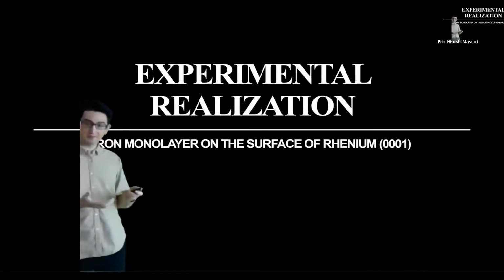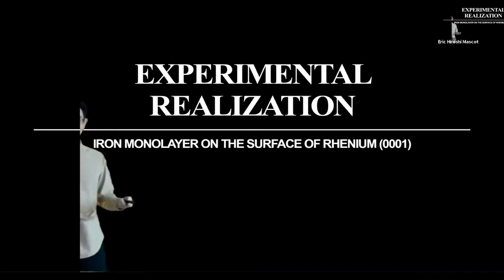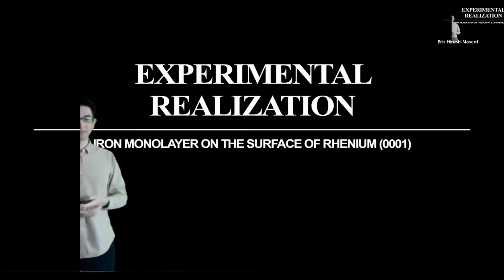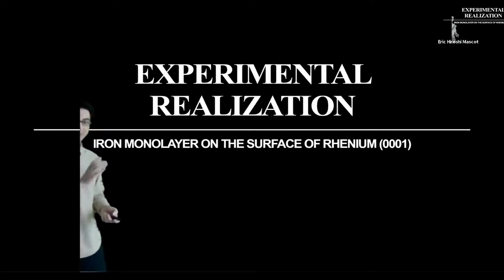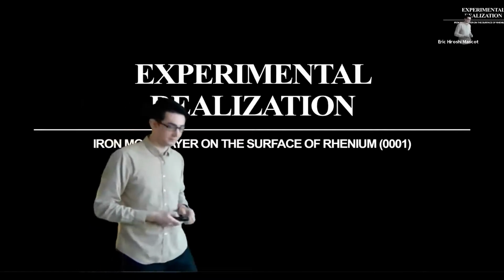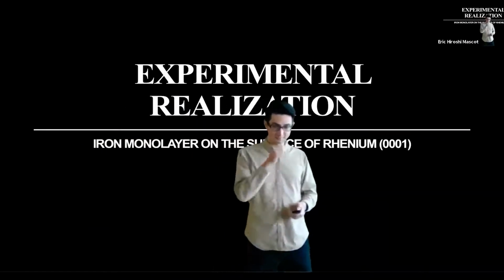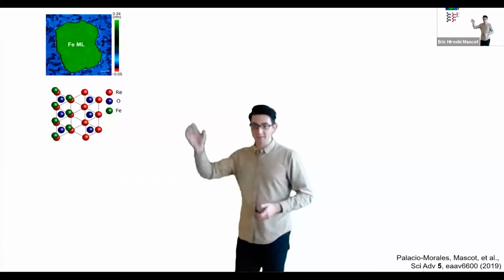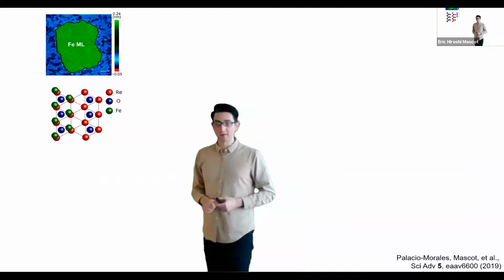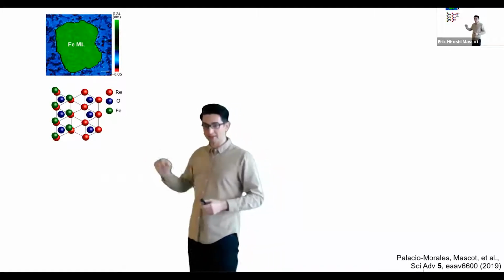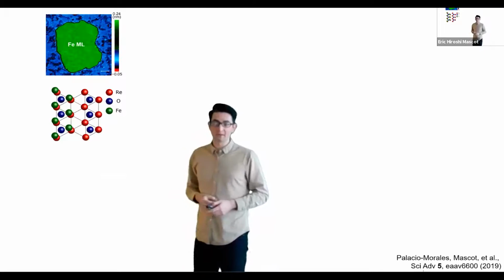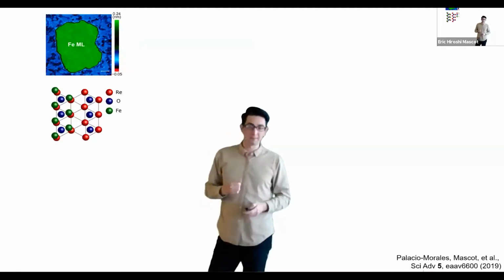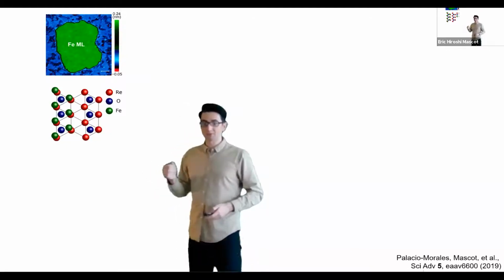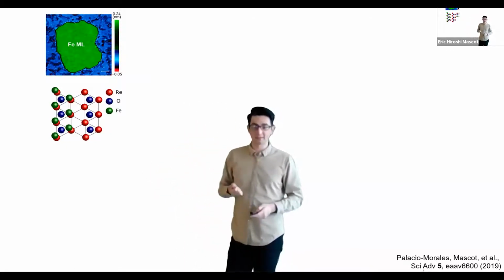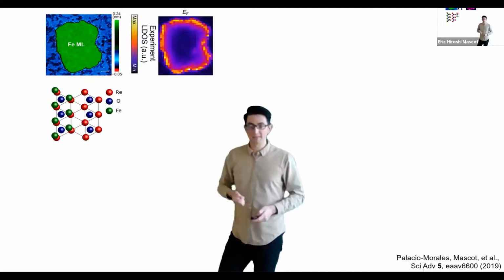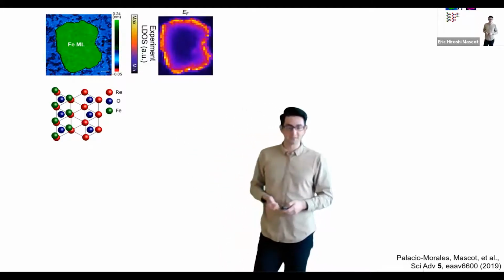So that's a theory. Do we actually see this in an experiment? We collaborated with a group at the University of Hamburg who grew these iron monolayer systems on the surface of rhenium, which is an S-wave superconductor. And so here's a topographic image of that iron monolayer on rhenium. And there, in this sample, there is an oxide layer that's a single atom thick. And they measure the local density of states using scanning tunneling spectroscopy. And they see this zero energy state localized to the edge of the island.